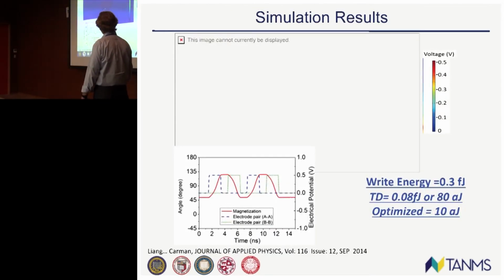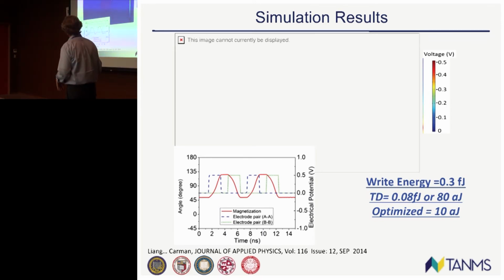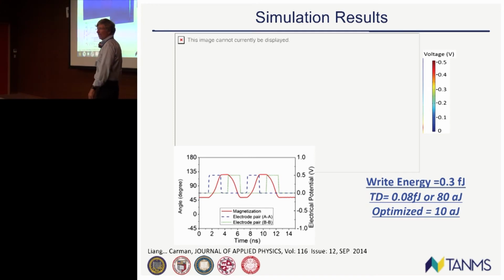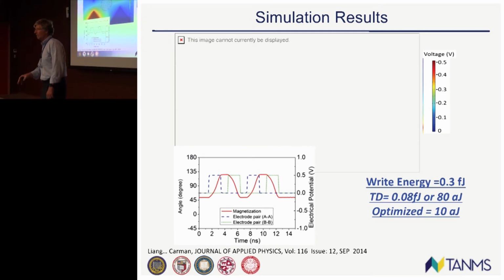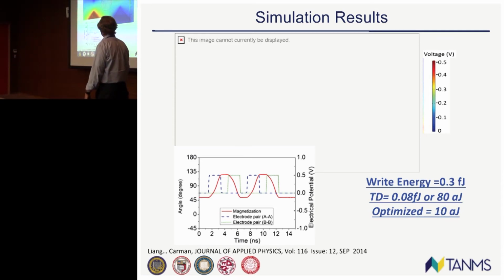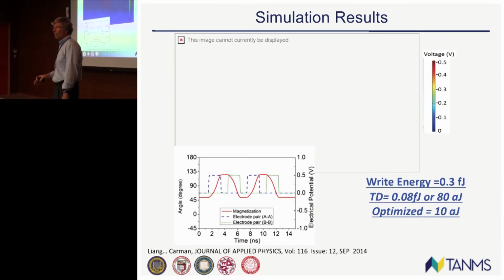So we designed this structure so you let them stabilize. The little red arrows are the spin states. You'll see these reds are the electric field. It rotates. We designed the states so that this is stable. Take the electric field off, you're at 50 kBT, it's stable, and you can rotate it back and forth. And guys, by the way, this is all slow motion. How fast does that rotation actually occur? About 2 nanoseconds. The other thing you may ask, well, what's the voltage that you're using here? It's on the order of 1 volt in that thin film PZT.